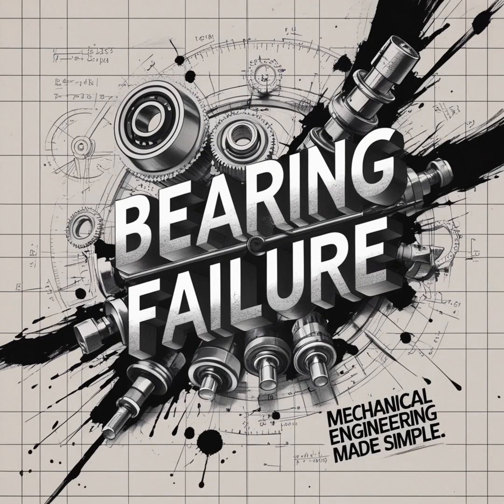Electrical erosion or fluting. This is a massive issue, particularly in variable speed electric motors running on frequency converters. Yeah. If the grounding is inadequate, the current finds the path of least resistance. Straight through the bearing. As the current arcs through that thin lubricant film between the rolling element and the raceway, it causes these microcraters. It's like thousands of tiny arc welds.